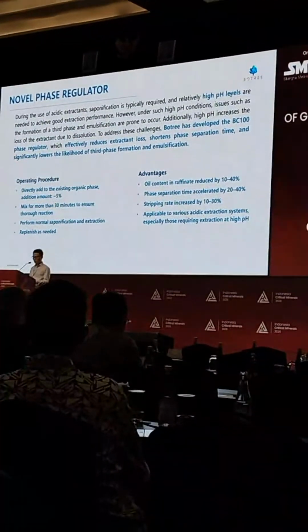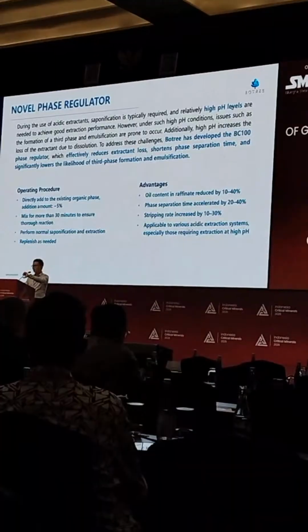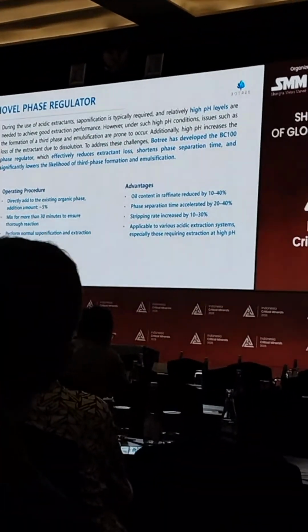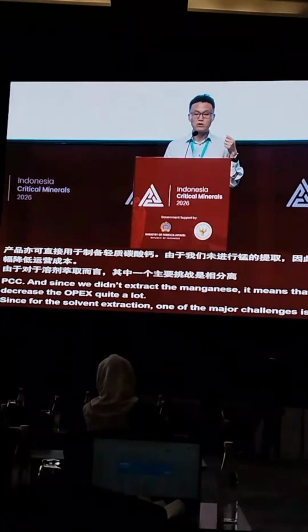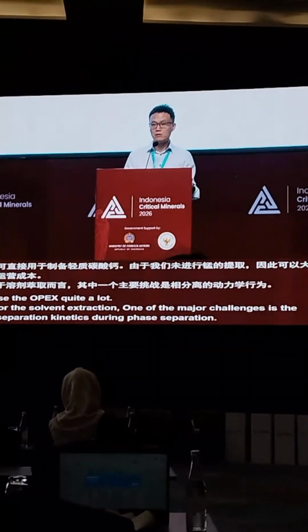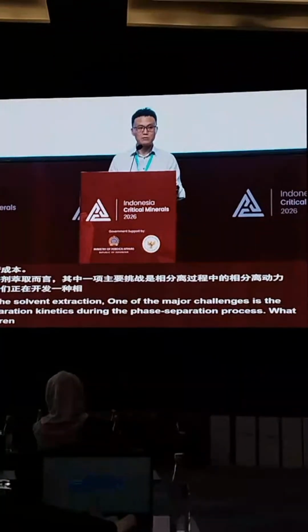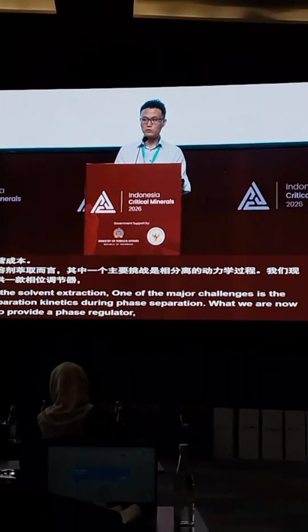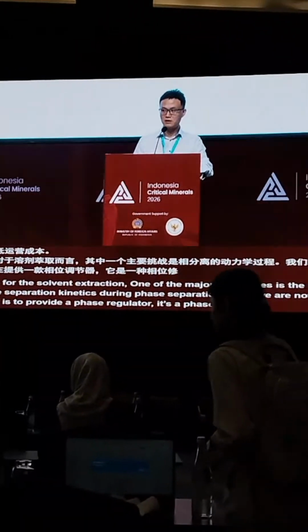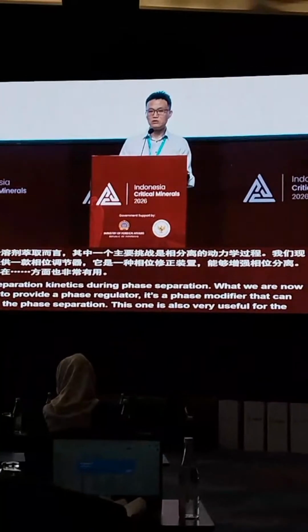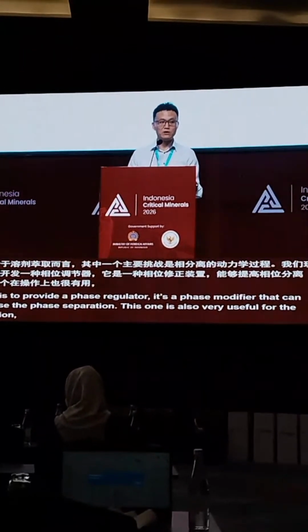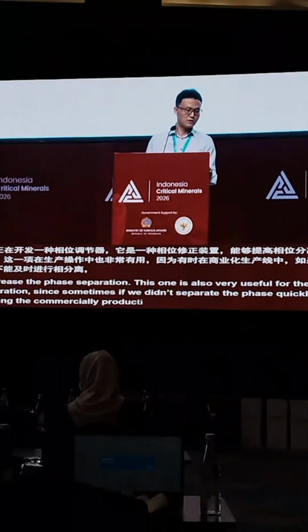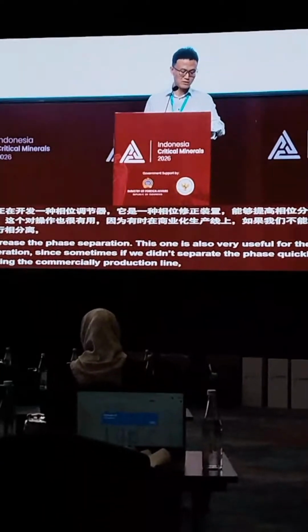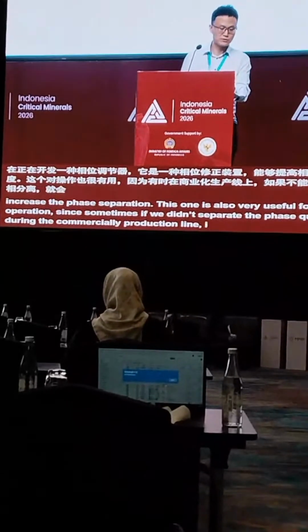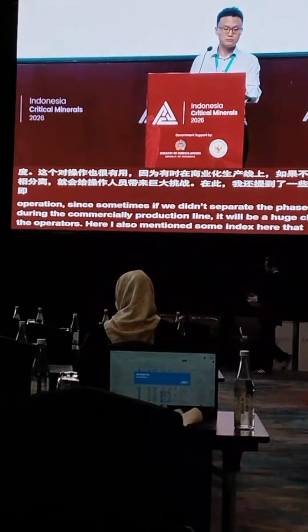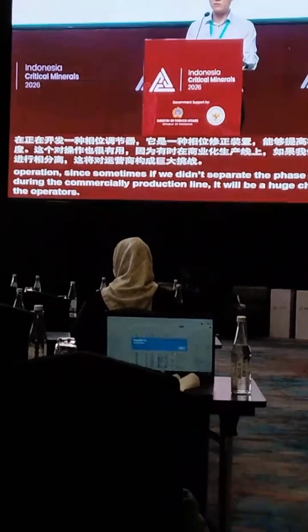For solvent extraction, one of the major challenges is the phase separation, the kinetics of the phase separation. What we are now doing is to provide a phase regulator, a phase modifier that can speed up the phase separation. This is also very useful for the operation, since if we don't separate the phase quickly in the commercial production line, it will be a huge challenge for the operators. And I also mentioned some index here that can help operations reduce the raffinate oil, which is a key parameter for the wastewater treatment.